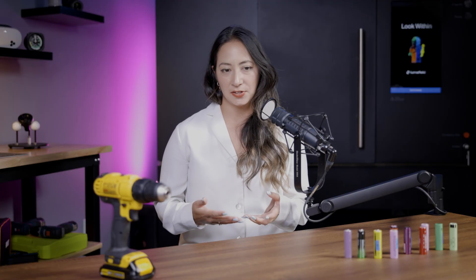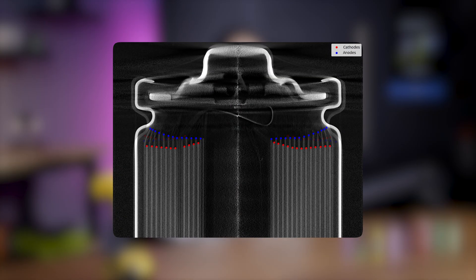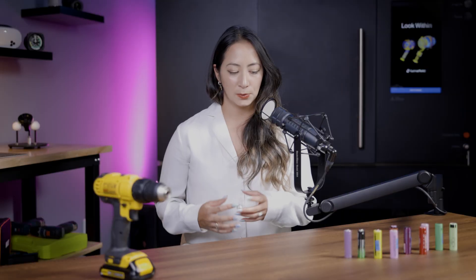Ideally, you really want to have that half a millimeter of overhang. If you have insufficient overhang, it really increases the risk of plating and dendrite formation. And actually having too much overhang can be a problem as well — not only is it wasteful of active material, but it also can lead to those extra-long anodes making contact with the can, leading to other kinds of shorts and performance issues later.